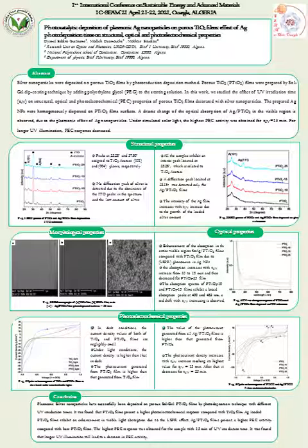Figure 3 presents SEM micrographs of pure TiO2 films prepared with and without PEG, and the film prepared with 25 minutes of UV irradiation time. The surface morphology of the film with PEG is rough and porous compared to the one without PEG. The white spots in Figure 3c represent the silver nanoparticles, which seem to be homogeneously distributed on the porous TiO2 film surface.